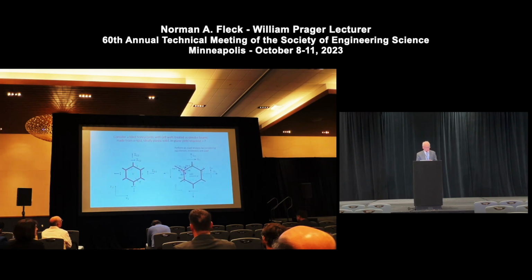We asked the question, what about the effect of volume constraint upon the yield behavior? And for this idealized case, one can write down an exact analysis and predict the yield surface, the initial yield surface. And what you find is the yield surface is very sensitive to the omega value, and particularly in the vicinity of omega 30 degrees, the yield response is very sensitive. One can derive the analytic equations for this.